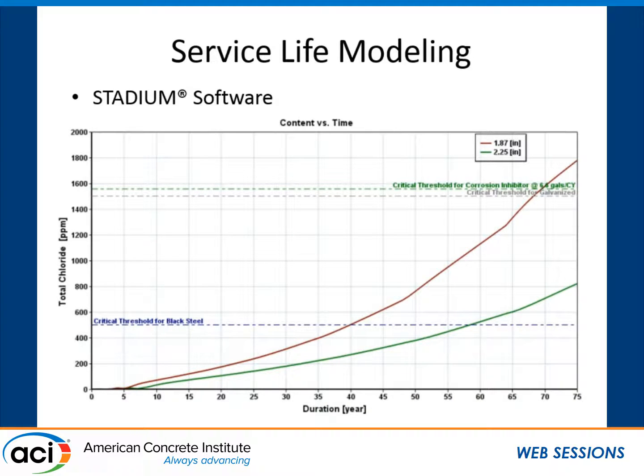The data itself would be modeled where you would have predicted chloride content, duration in years, and then eventually critical levels of chloride that would cause corrosion, whether it's do nothing with the black steel, or if you would use galvanized or different levels of corrosion inhibitors, you'd have an extension. So as time goes on, you'll see that at this concrete cover, predicted chlorides without any protection means would not make the 75 years. However, putting in a protection system, a calcium nitrite or a different type of reinforcing, will definitely get you with the propagation time that amount on a deterministic basis.